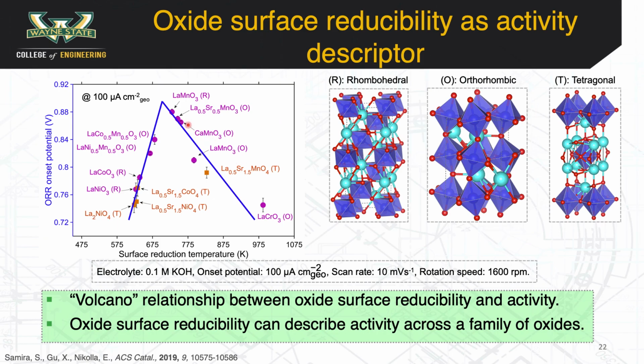What is also interesting is that for n equal to infinity type perovskite oxides, the oxide surface reducibility, in terms of surface reduction temperature, captures effects from the A site composition of these oxides as well as the B site composition, thus making it universal in describing the activity of n equal to infinity type perovskite oxides.